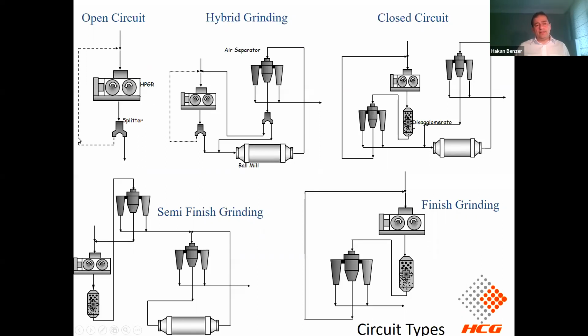Chronologically, in 1985, when it started, the HPGRs automatically started running in open circuit mode. So it was used specifically for feed preparation to the ball milling operation. Afterwards, the operators noticed that because of the requirement of adjusting the feed going into the roller press, they split some of their products back onto the HPGR in order to increase the confined bed conditions. So they needed some fine materials. This brought the idea of the hybrid operation, because the HPGR is running with a ball mill, and the ball mill is running with a dry classifier. Some portion of the very fine material can be sent back to the HPGR to increase the compressed bed conditions.